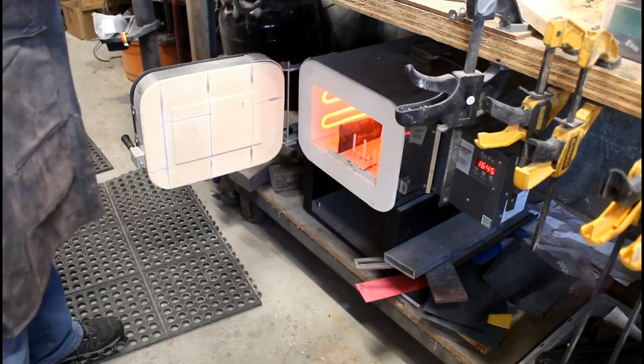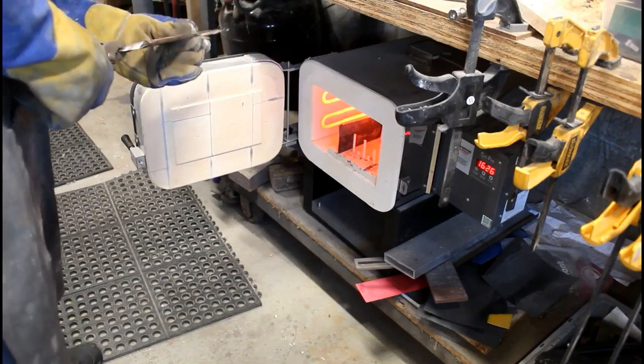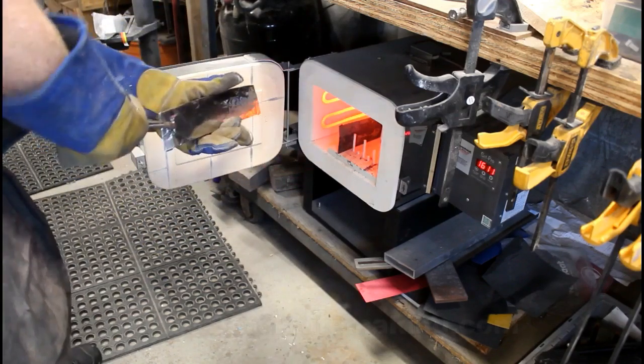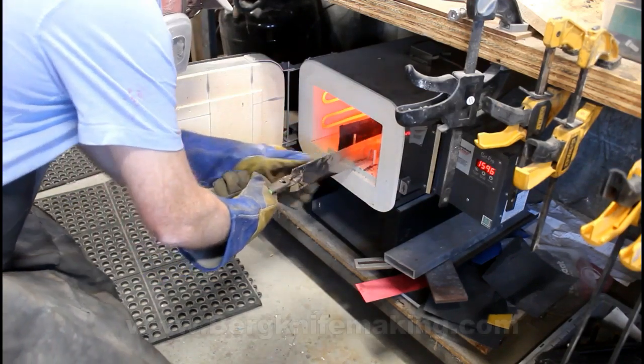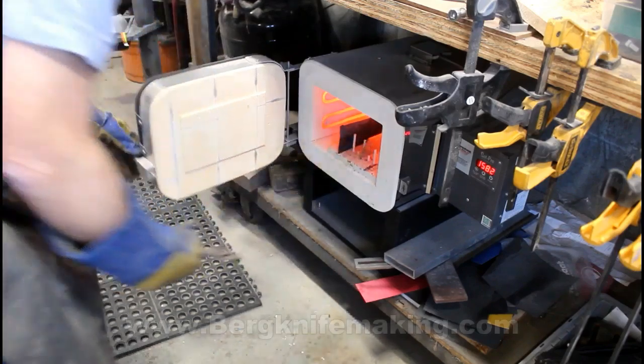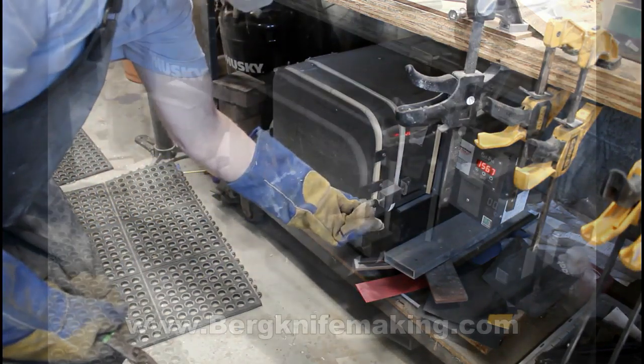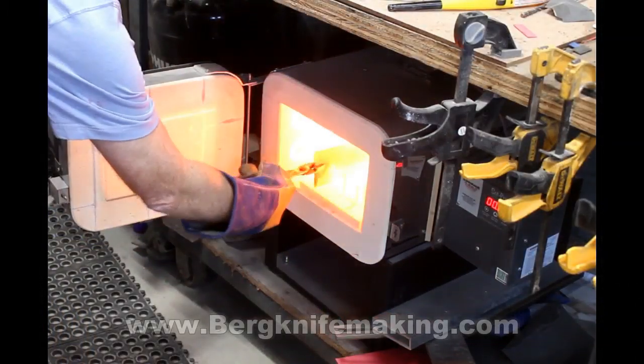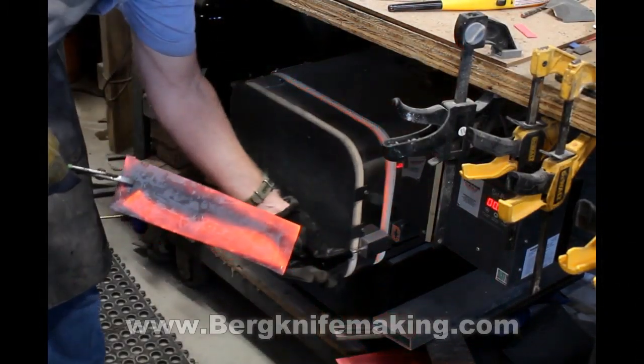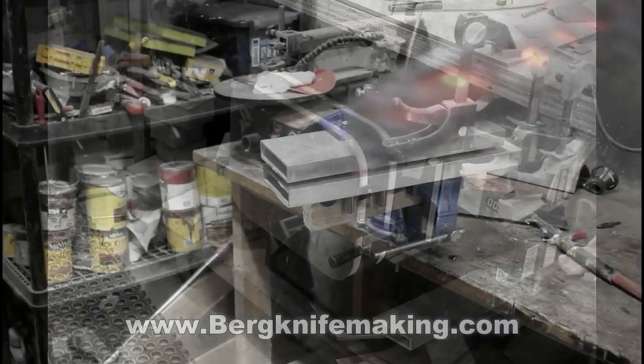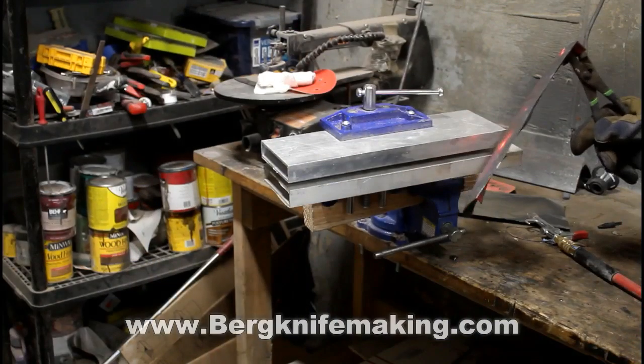So these blades are going into the heat treating oven. They're going to stay in there. They're going to get up to temperature, and then they're going to soak for 15 minutes. And then I cool these blades, or quench the blades, called plate quenching. I clamp them between 2 aluminum plates, and then I blow compressed air over and under and around the blade to get it to cool off as quickly as possible.